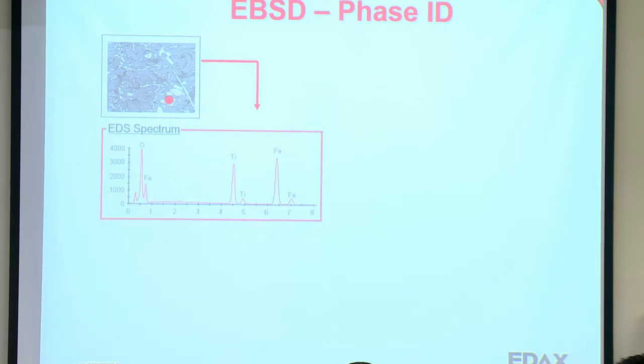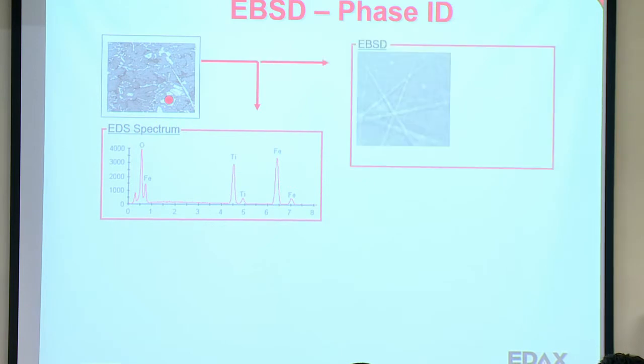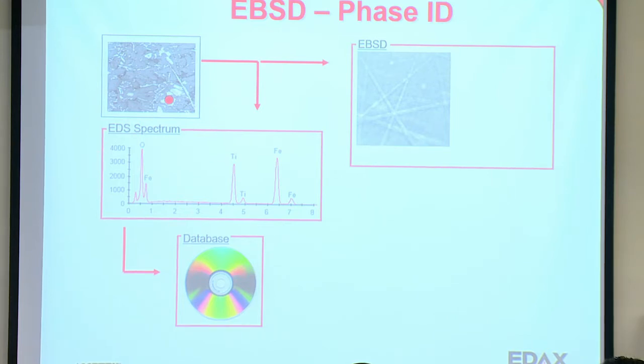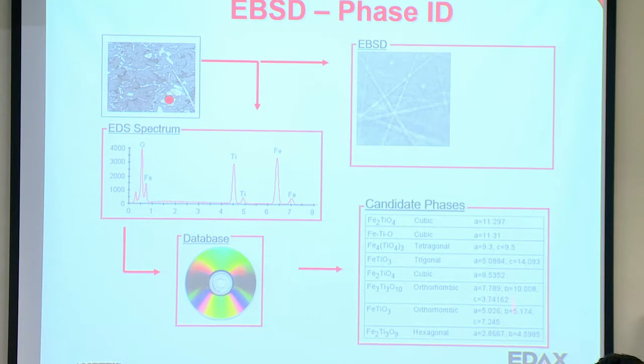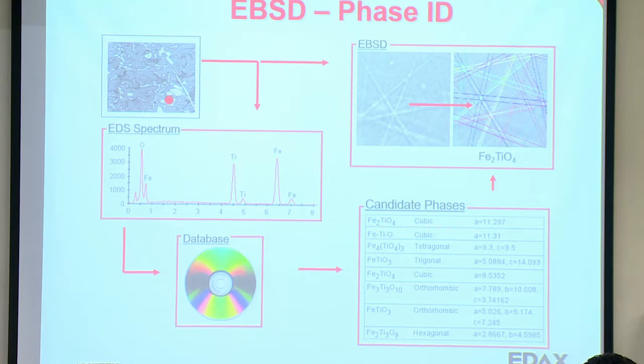From that, then, you capture an EDS spectrum to learn the chemical composition of your sample. In this case, it's primarily made up of titanium, iron, and oxygen. You capture an EBSD pattern from the same point, go back to this EDS spectrum, and go to some database. And there's a lot of databases out there, and I'll talk about those later. But this is a chemical database, and from that we know the phases. So from that database, we take the various parameters, such as the lattice parameters and other factors, and we use that information to try and index this pattern. And if you do that, you can see then that this top one seems to be the best match, Fe2TiO4. And so we can use all this information to get a positive identification of the phase.